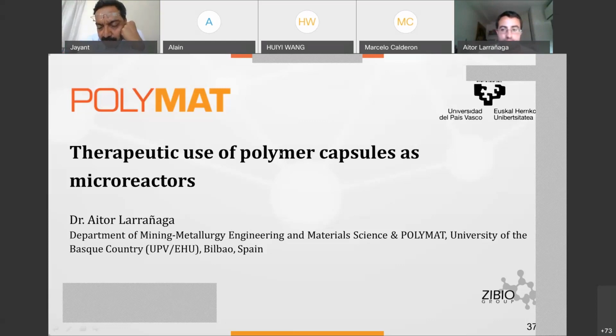Yeah, and then you have Marcelo, your question, please. Yeah, I was just wondering if you can have any strategy where you can enhance the interplay between the antioxidative activity from tannic acid and catalase. I never checked that, to be honest. I think what we try to do is to maximize the amount of catalase that we encapsulated, and we found that when we try to encapsulate more, we completely lost the possibility to create the template. So I tried to maximize, but I never checked this interplay between the surface functionalization with tannic acid and encapsulated catalase. But this is something that we could study in the future.